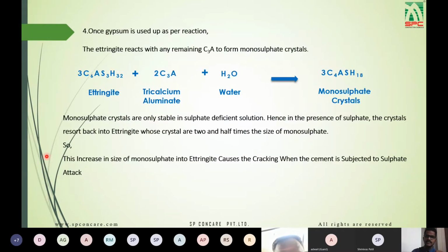As per the first reaction, the reaction of tricalcium aluminate, gypsum and water, ettringite is produced. Once the gypsum is used up as per the first reaction, the remaining ettringite reacts with the tricalcium aluminate in the presence of water to form monosulfate crystals. Now, the monosulfate crystals are only stable in a sulfate deficient solution. Hence, in the presence of sulfate, or if the concrete is subjected to sulfate attack, the crystals revert back into ettringite, whose crystals are 2.5 times the size of monosulfate.